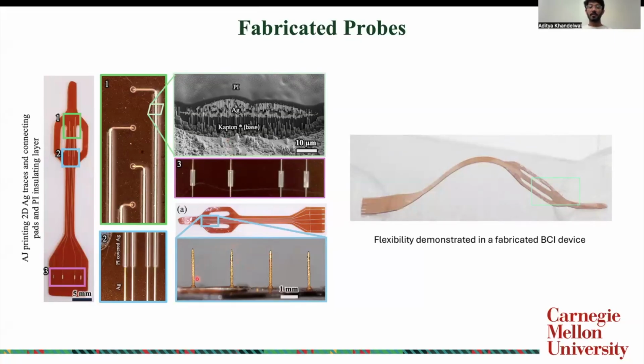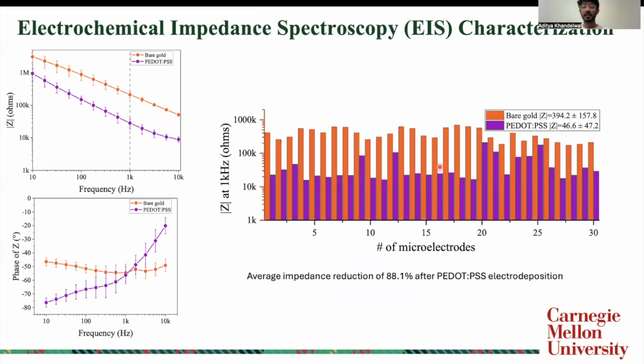In this image, you can see the fabricated electrode probes. In the image on the right, you can see the flexibility demonstrated in a fabricated device. So you can see there is no delamination of the tracks or the gold probes, which basically ensures that the device is flexible. Now we talk about the electrochemical impedance spectroscopy of the device.